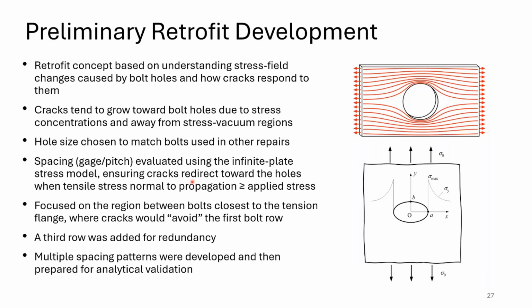The reason is that, as shown here, the stress field around a bolt hole, or in fact any hole, if we look at the hole in the direction of stress, in a plane perpendicular to that direction, you will find hot spots of stress on the sides of the hole, and in front of the hole you have sort of a stress vacuum. We know that the stress intensity here is about 3 times the far field stress. We also know that if we were to have a crack in an infinite plate, coincident with that plane perpendicular to the direction of stress but aligned with the center of the hole, that initial defect will grow towards the hole.